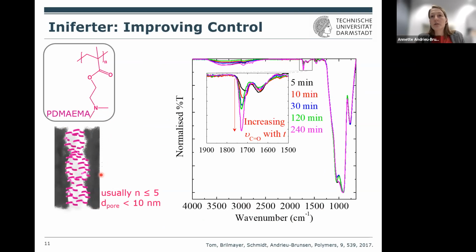And you cannot do this if you vary, let's say, the polymerization time for any sample, because you just need a lot of material. So what we usually do is that we measure ATR-IR. This is nice because you can normalize the spectra to the silica band, and then you can look, for example, at the CO vibrational band of your polymer. And here in this example for the PDMA-EMA, you see nicely that you can control the polymer amount in these films by polymerization time, for example.